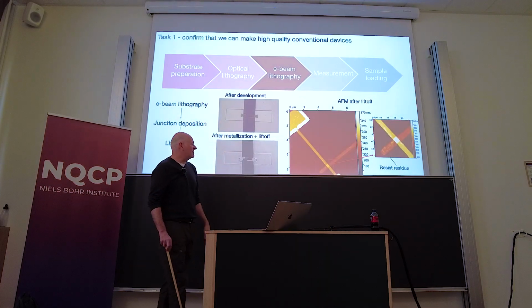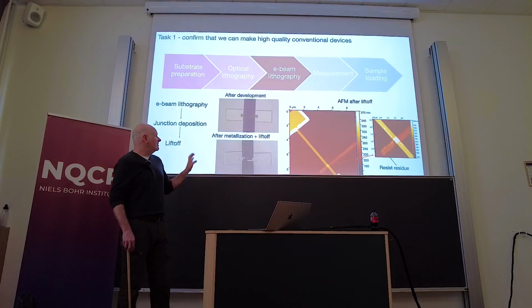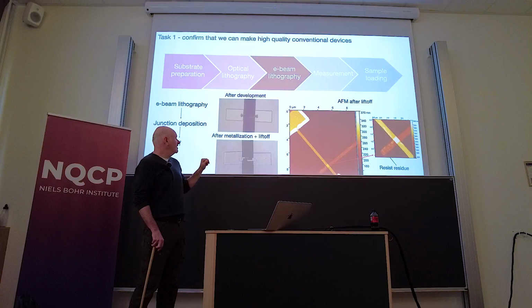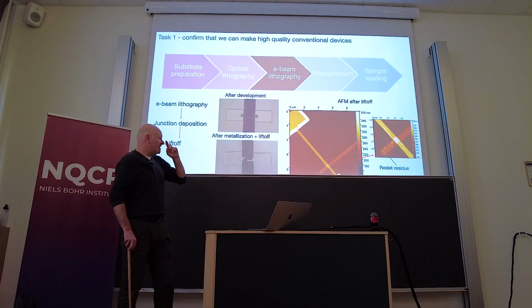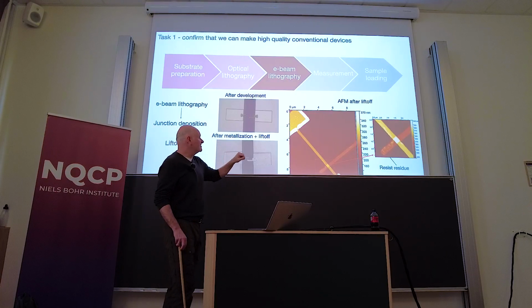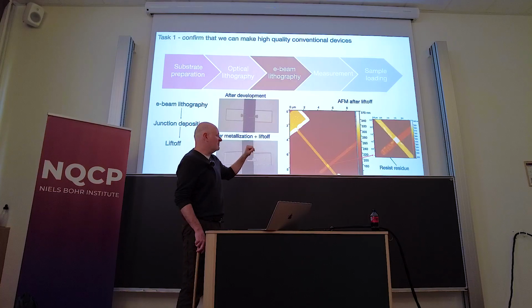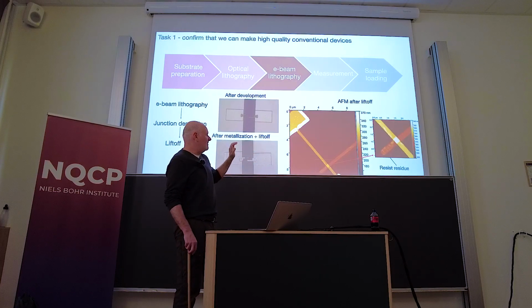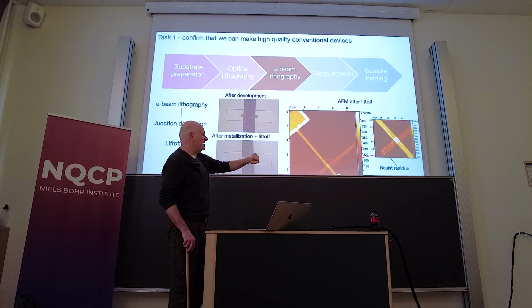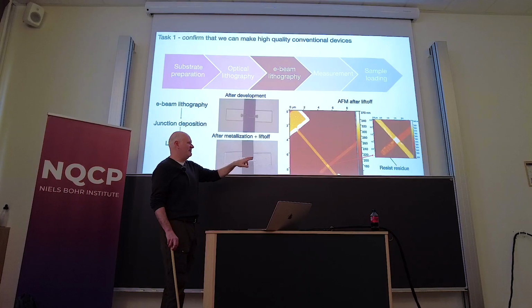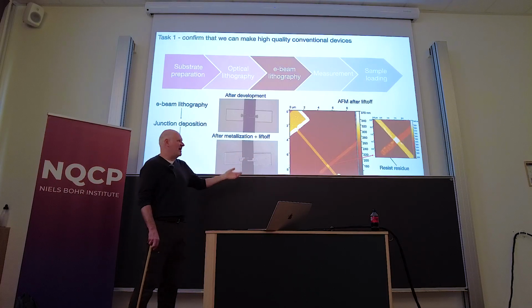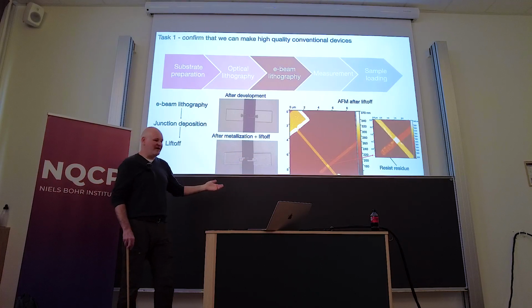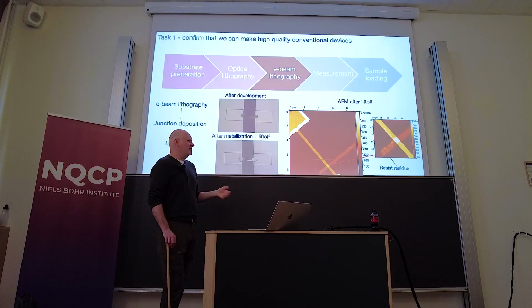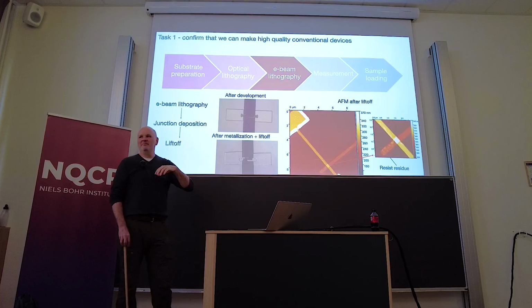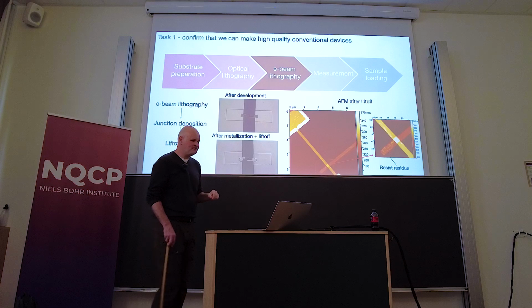Then we do E-beam lithography. So deposition and liftoff of aluminum. You can see these are AFMs showing just essentially what you would expect, relatively flat. But if you look at the zoom in, you can see that if you're not careful, you end up with resist residue. So we went through great efforts to remove that resist residue, trying to be as gentle as possible so that we didn't completely bombard the surface with oxygen plasma.